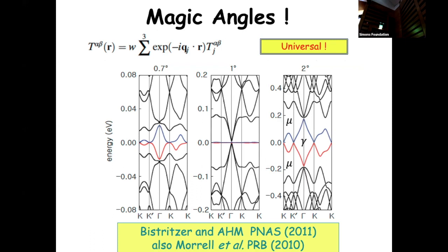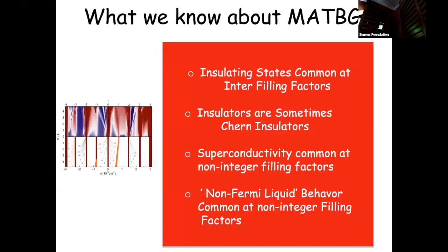And when we followed this recipe a number of years ago together with Rafi Bistritzer, we got a surprise that we didn't anticipate. Unlike the TMD case, in which the bands just get narrower and narrower as you make the lattice constant bigger and bigger, in this case the bands get flat at a certain set of discrete twist angles, and then they get broad again, and then they get flat, and then they get broad, as a result of an interference between the tunneling back and forth between the layers and the tunneling between sublattices within a layer, which is responsible for the Dirac dispersion. So there's nothing like an atomic orbital in this system.